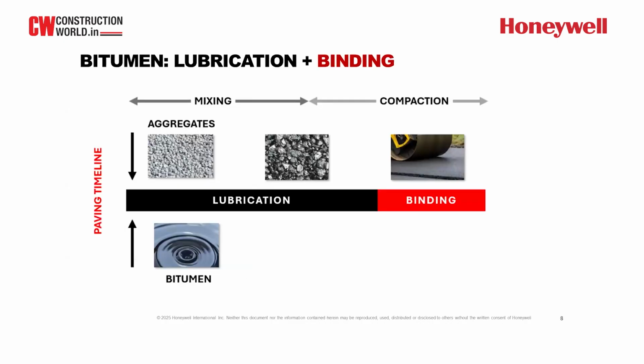Okay. Yeah, this slide shows how bitumen acts as both a lubricant and a binder, right? This plot is a very simplified diagram of the entire paving operation. First, at the asphalt plant, you blend the molten bitumen with the aggregate, different size aggregate based on your gradation, to produce the asphalt mix. Then you use a truck to transport the asphalt mix to the paving site, and transfer it to a paver. Then the paver will spread the asphalt mix as a thin layer at the top of the road, right? The foundation or the top layer.